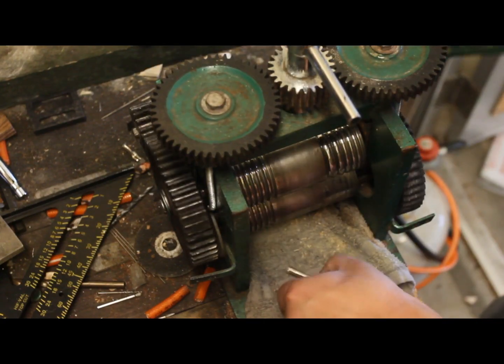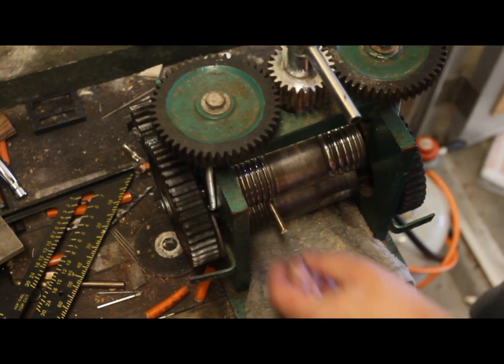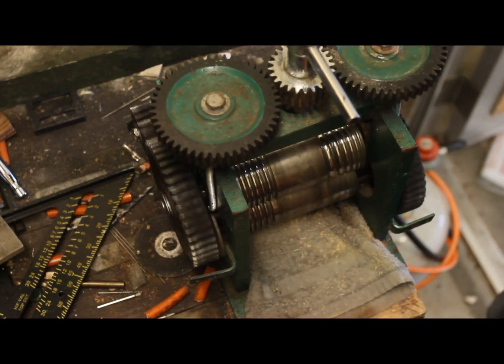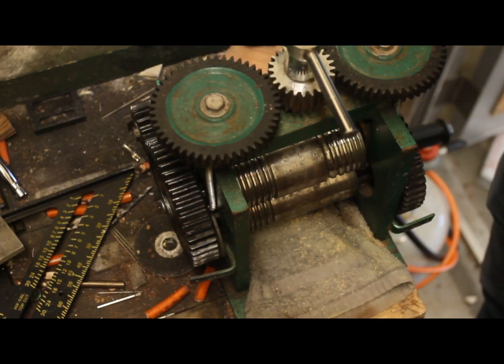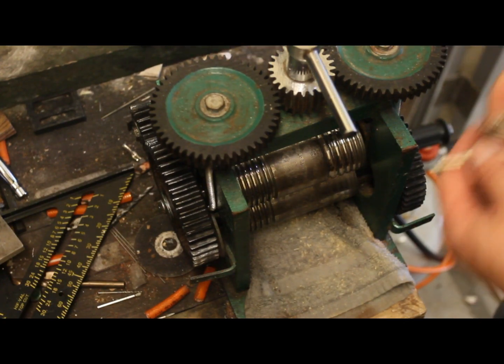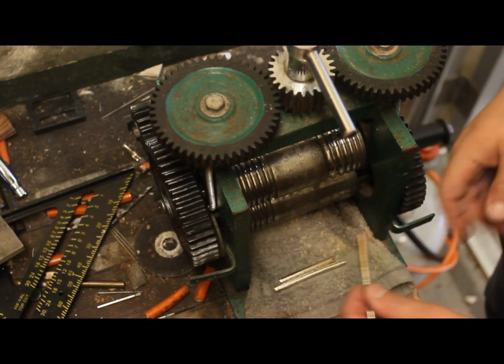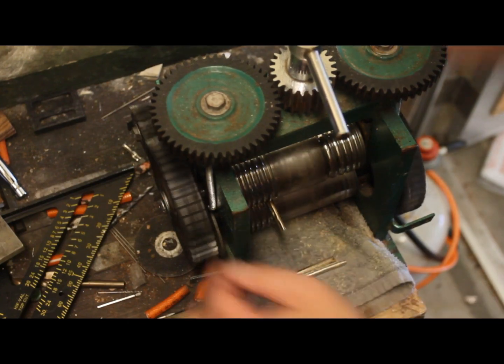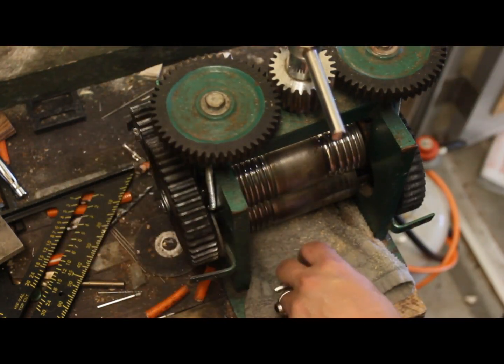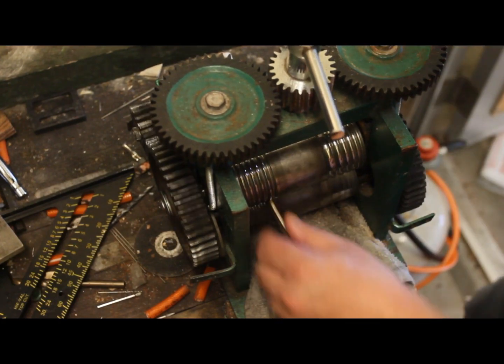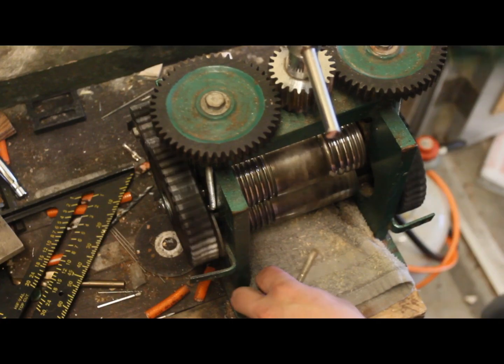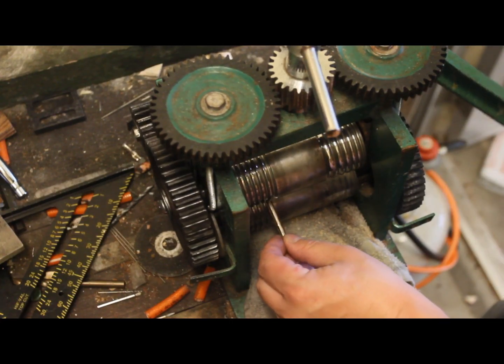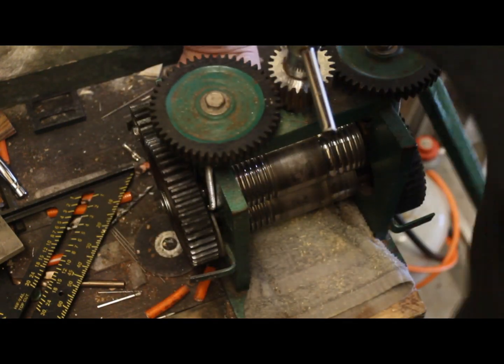When you're making square stock, it's really important after the first pass to rotate it 90 degrees so that it stays square as you bring it down in size. It's also important, depending on your rolling mill, how big of increments of adjustment you make. That's that turn at the top. So when I'm doing square wire, I can usually do about quarter to half a turn. You don't really want to go too much past that, or you run the risk of crushing it too fast, which can cause cracks to appear in your ingot.